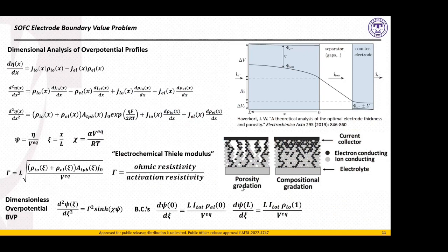Now we wanted to formulate a problem that could be solved readily so that its outputs, when they are fed to an optimization algorithm, don't take, on the order of days or weeks to solve. As some groups have done, they have reconstructed the electrode geometry at the pore scale, doing a full tomographic or three-dimensional reconstruction, and then simulated this through multiphysics and FEA. But those simulations take quite a while to run, and if we're going to sample through thousands of individuals based on a material set of interest, then we want to study this problem in a reduced order environment.